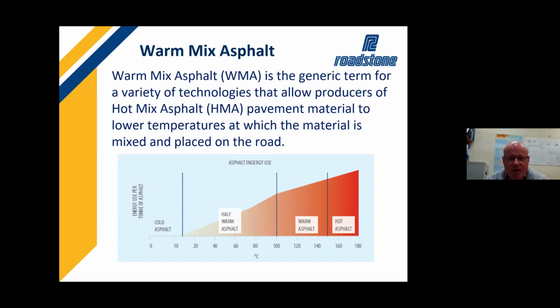One is that it extends the production temperature envelope and allows the aggregates to still be coated with a reduced mixing temperature, and allows the bitumen to flow and wrap the actual aggregates. And then after that, it allows the materials to be transported to site at those lower temperatures, and on site it opens up the compaction envelope, which allows the materials to be compacted on site at a larger range of temperatures.